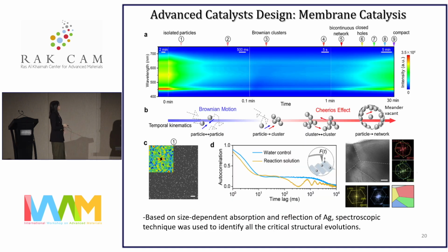Okay, let me quickly go through the formation mechanism of the membrane. So by exploiting the size-dependent absorption and reflection of silver, we have developed a fast spectroscopic method to identify all the critical states in the formation of the membrane. So essentially, the successful membrane formation depends on 2 stages, that is Brownian as well as Cheerios effect. So we start off with the Brownian motion, which is a random motion and collision between suspended particles. And this basically dominates the